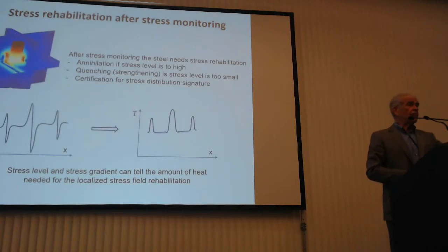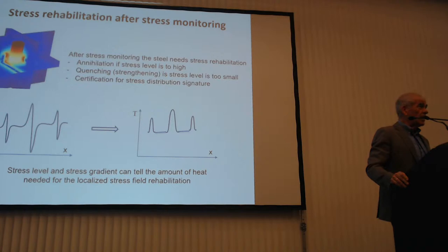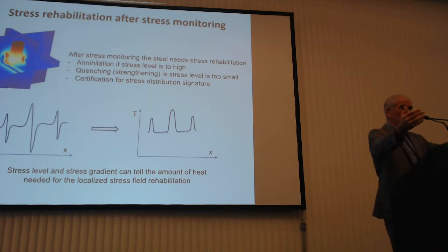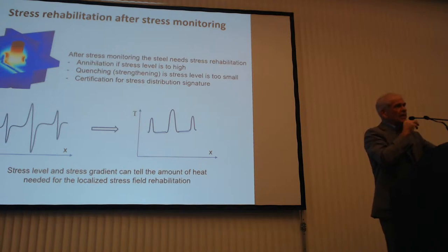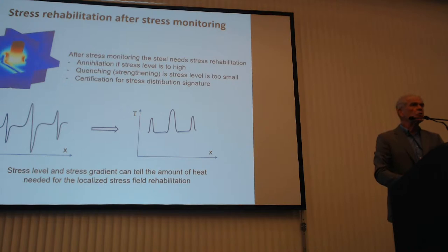This was not enough for us, because we wanted to not only monitor the residual stresses and therefore the possibility of cracking, but we wanted to correct such possibility. I mean, to return back the health of the steel. And we wanted to do that using not the classical thermal treatment, but localized thermal treatment. And we did that with respect to induction heating.